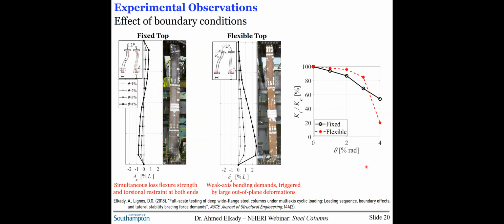Now, this full-scale test specifically provided the unique data that helped quantify the effect of end boundary conditions, because prior to this, most of the tests involved either fixed boundary conditions or this cantilever boundary condition as a simplification. If you look here at 2 identical column specimens but with different boundary conditions, when it comes to the moment rotation behavior, the differences in strength were minor. However, the differences related to the loss of stiffness were observable.